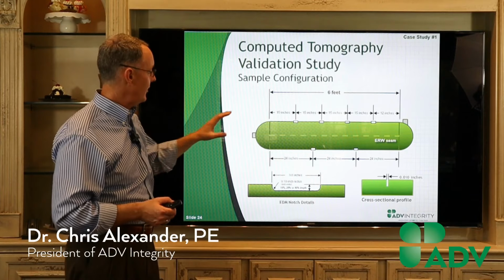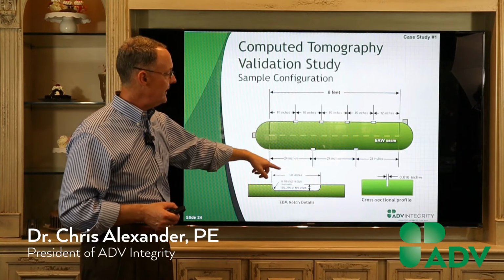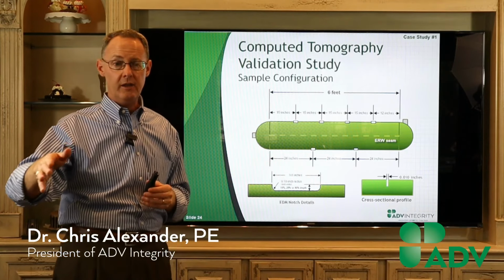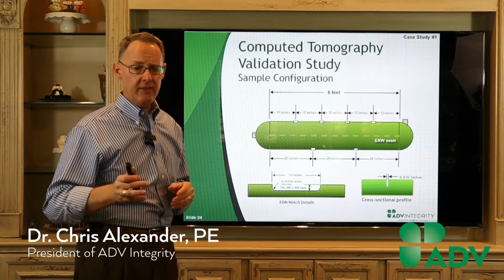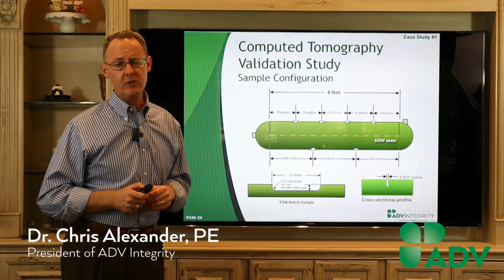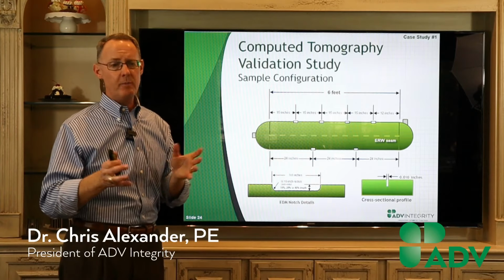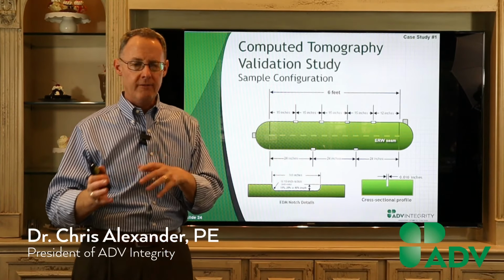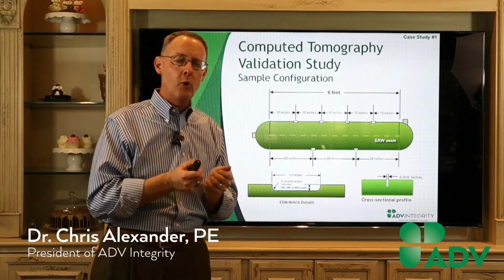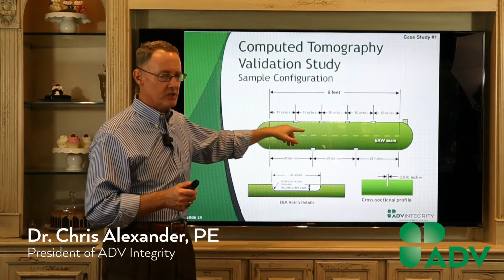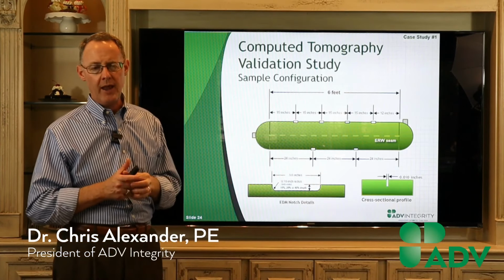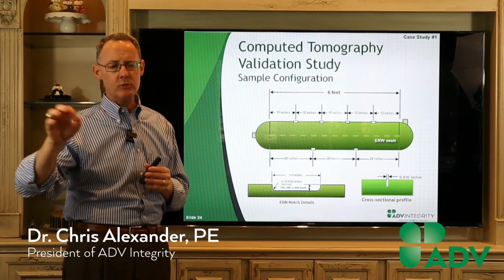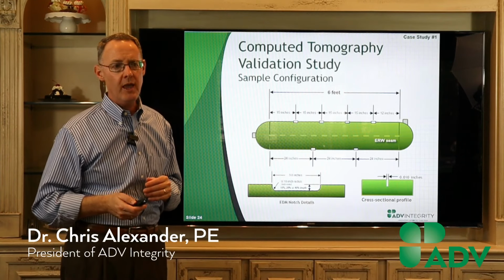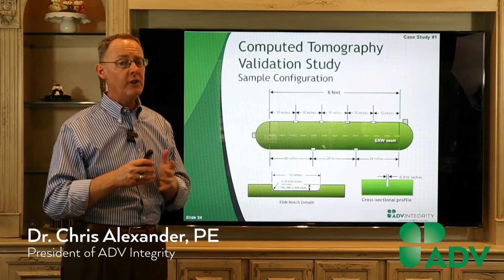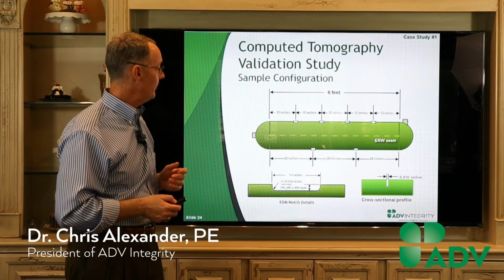So we took a pipe sample, 12-inch. We put some EDM notches in it. We did the pre-cycling to generate cracks. And then we sent it over to Inspection Associates, and they did their magic and they did some inspection work. Then we got the pipe back, and we broke all of these notches open to see what kind of crack growth we had, and we compared them against what Inspection Associates had determined. And what we found was there was really good correlation. You'll see that here in a couple of minutes.